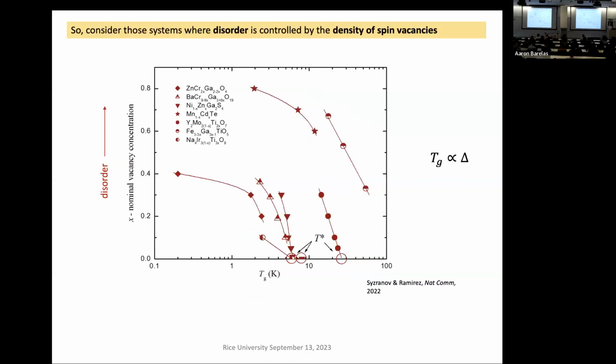But let's relate it to materials components. So here I'm going to plot Tg versus disorder, or the nominal vacancy concentration. And you can see that all the data went here. So at this point, Sergey said, well, that implies that there's an energy scale in the pure system. Right? It's sort of obvious.